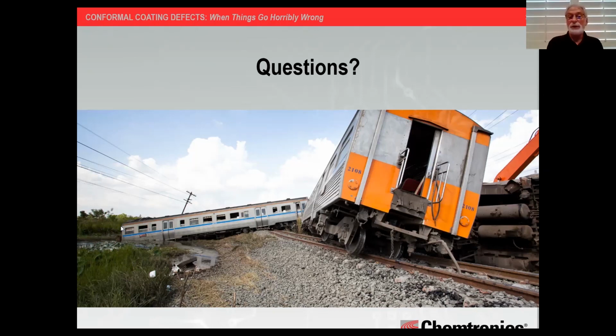Oh, well, if you're getting dendritic growth, that means that you've got some type of ionic residue underneath the coating. Hopefully the coating mitigates intrusion of liquid moisture, liquid water. It resists that. However, one thing you have to be reminded of is that all coatings are permeable. All coatings will breathe to a certain degree, some more so than others, even within a category. Like within acrylics, there's different transmission rates. It allows that moisture vapor from the outside environment, the humidity, to come in. It also allows it to go out. Some are better at that than others.